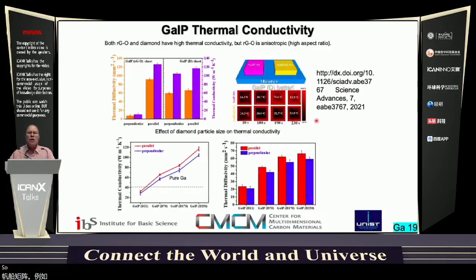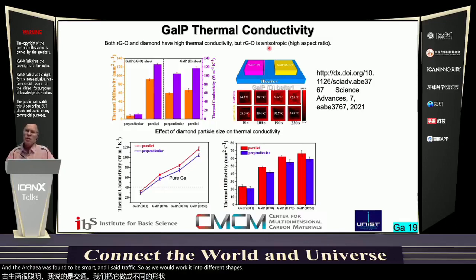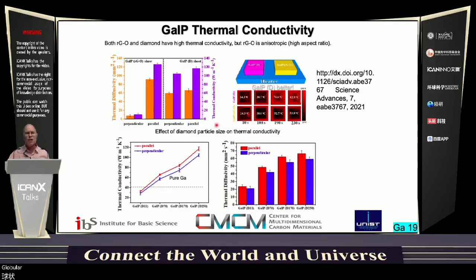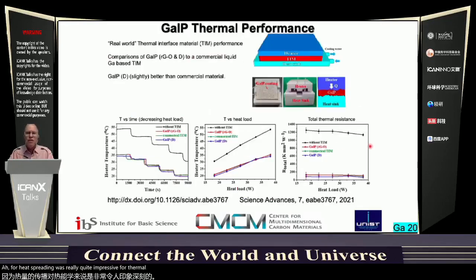So we could learn that both RGO and diamond particles imbued the composite with a big jump in thermal conductivity. And the RGO was found to be more anisotropic. As we would work it into different shapes, it was tending to behave like a platelet, and the diamond particles are more globular. So there was a significant jump in thermal conductivity, and thus the performance of this gallium putty material with diamond for heat spreading was really quite impressive for a thermal interface material.